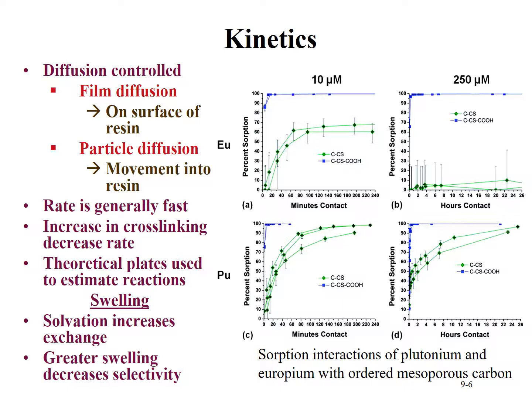And as you can see, there tend to be differences shown here with concentrations and the time it takes to reach a given plateau. Here for 10 micromole, this plateau time is on the order of tens of minutes for the functionalized mesoporous carbon, and for the non-functionalized, it reaches a plateau around 100 minutes for the europium.